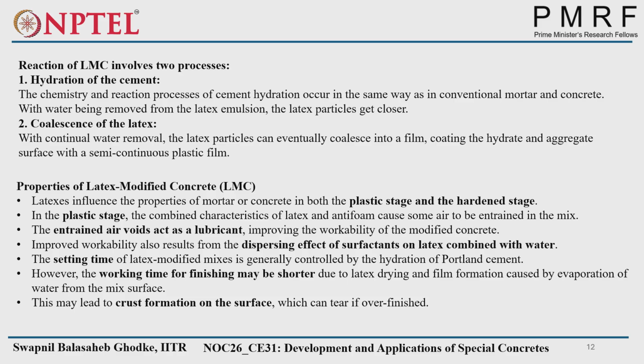Another thing is that workability also improves by the dispersing effect of surfactants. Whatever surfactants we are using have a dispersion effect. Dispersing effect means the particles will repel each other, creating distance between each other. That again creates flowability or workability. Setting time of latex modified mixes is generally controlled by the hydration of Portland cement. Here, setting time is not controlled by the polymerization process. It is controlled by the hydration process because we are using the water for hydration purposes.